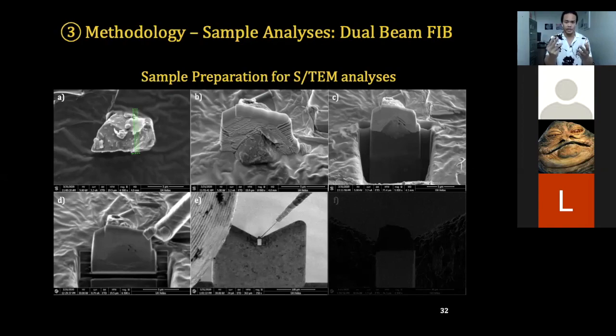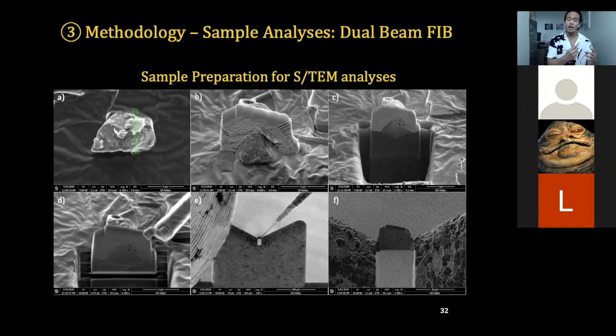So as you can see, there's our needle. The small tiny dot in the center is the sample, and then the thing at the bottom is the copper grid where it is attached. After it's been attached to the copper grid using platinum, the needle is then detached. And so image F shows a zoomed in image of image D, which shows our sample being attached to the copper grid, and then the needle has been cut free.